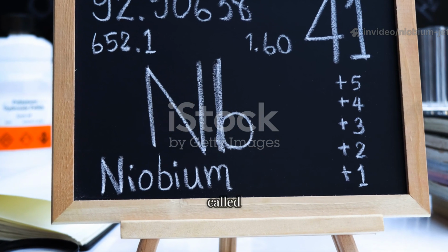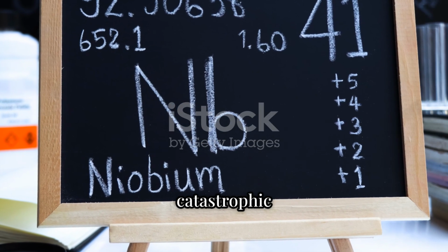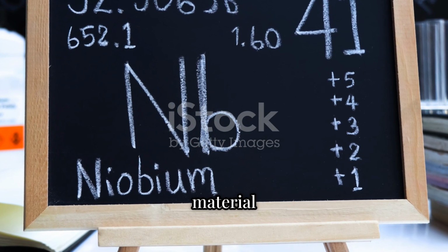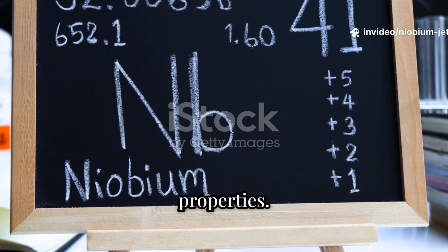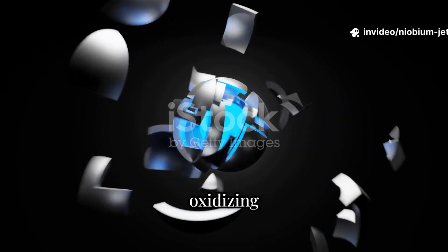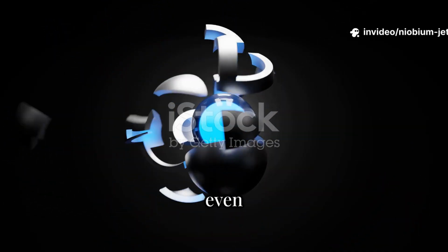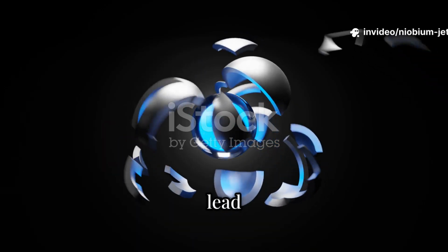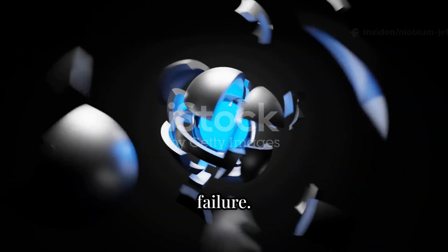This phenomenon, often called pest oxidation, can lead to a catastrophic degradation of the material and a rapid loss of its mechanical properties. Exposure to this oxidizing environment is cumulative, meaning even short but repeated exposures can lead to premature component failure. Another challenge has been the inherent room temperature brittleness in some niobium alloys.